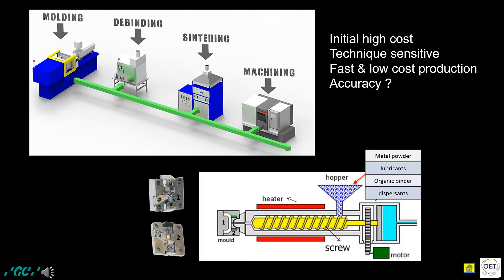In the following figures, the MIM process is demonstrated to clarify the manufacturing technique. Initially, a powder containing metal and other materials is inserted into heating chambers and heated to fluid status. Then, under high pressure, the metal is injected into cavities to gain the bracket shape. The next two steps — de-binding and sintering — are meant to extract unrequired materials and maximize the condensation of the raw bracket. In these last two steps, substantial shrinkage is expected. The last step is cleaning and smoothing. The accuracy of the bracket is highly dependent on the sensitive procedures and the quality of the metal powder. The cavities also have a limited working lifetime.